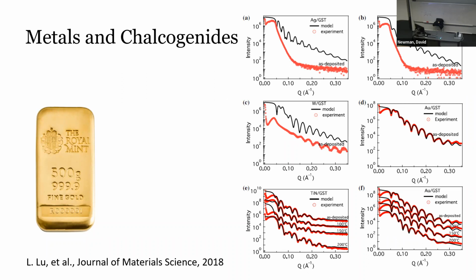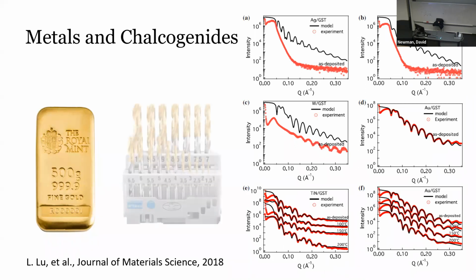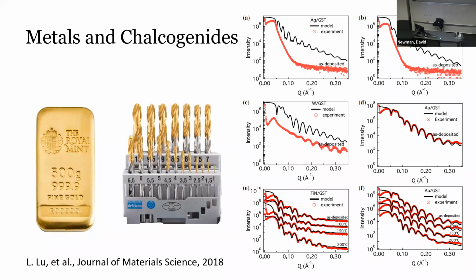It also happens that titanium nitride behaves like a plasmonic material. It has a negative real part to the dielectric function in the visible spectrum. And that's why, for example, titanium nitride tipped drill bits look like gold. Their optical properties are very similar to gold in the visible spectrum. So I think titanium nitride is a good choice. Also, is this going to work?